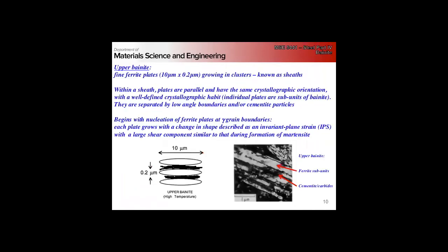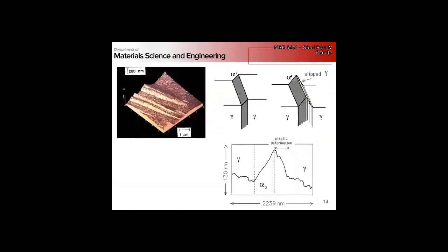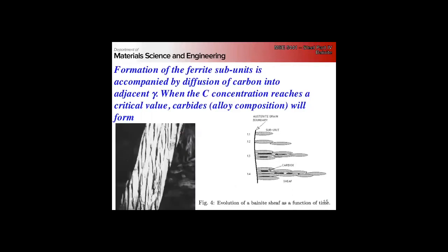The difference between upper bainite and lower bainite: it's a displacive mechanism, so we have shear. We see it in the surface relief. But unlike Widmanstätten, where we grow two variants, we have our bainite, and then we cause plasticity in the austenite next to it. So the ferrite regions in bainite have very strong dislocation densities. And remember the